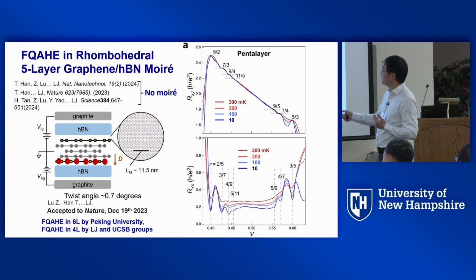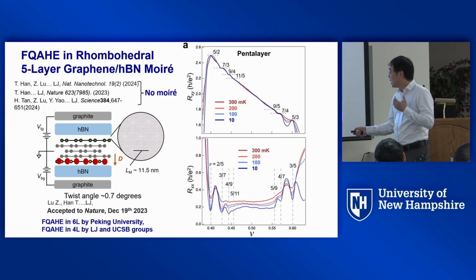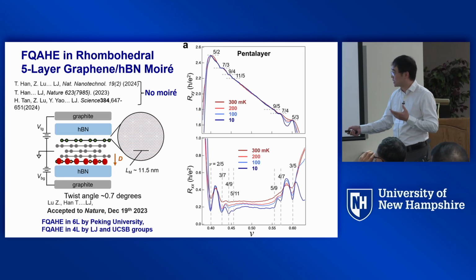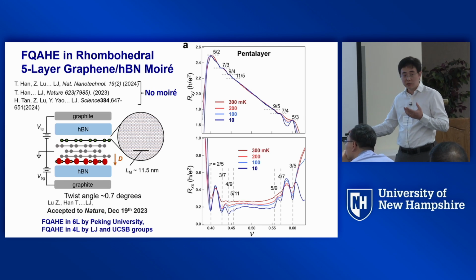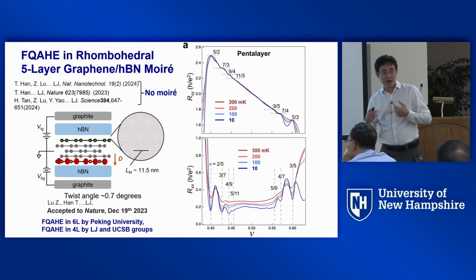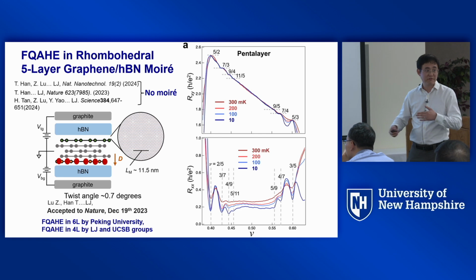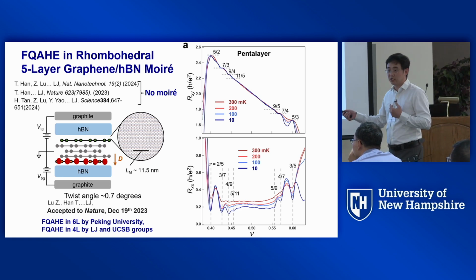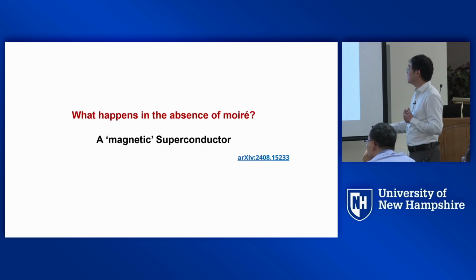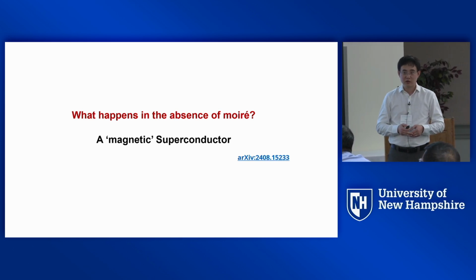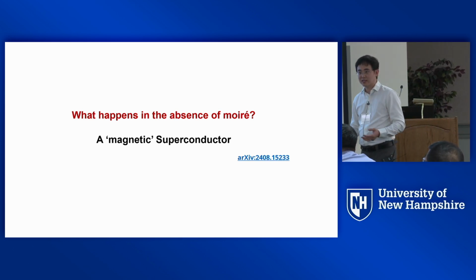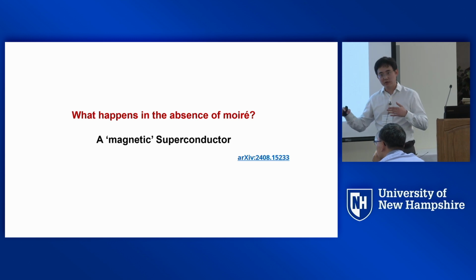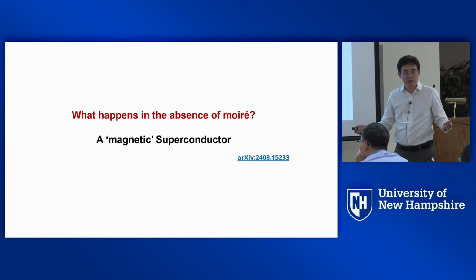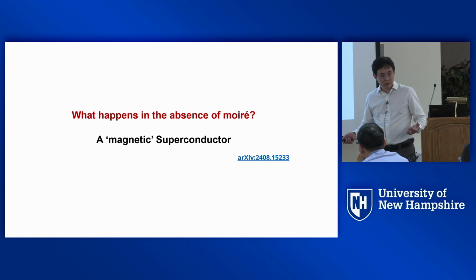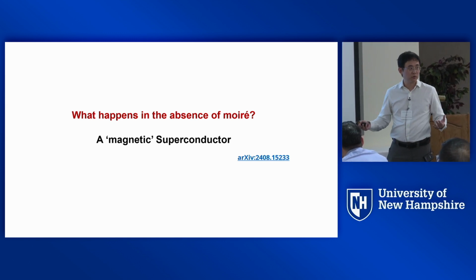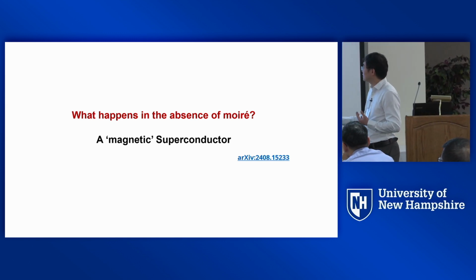And this phenomenon in rhombohedral graphene hBN moire has been reproduced in the 6-layer version by a group at Peking University, and in 4 layers by us and Andrea Young's group at Santa Barbara. So this is a family of FQAHE materials. Okay, that's moire. The rest of my talk is going to be about no moire. As I said, without moire, you already get flat band, you already get Berry curvature. So why don't we look at what happens in the absence of moire, more like the conventional crystal wisdom? And what we found there is a magnetic superconductor.